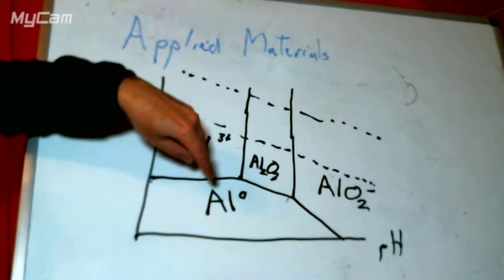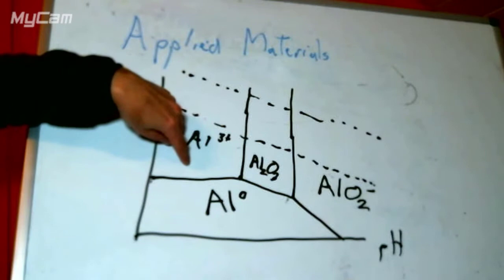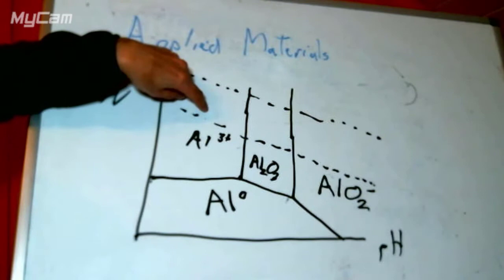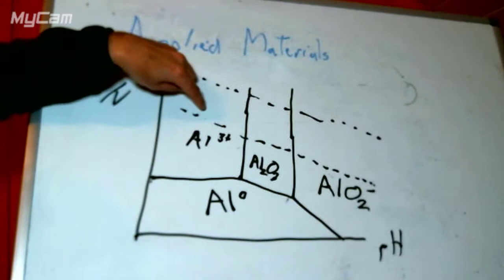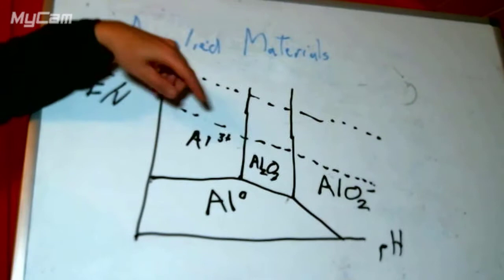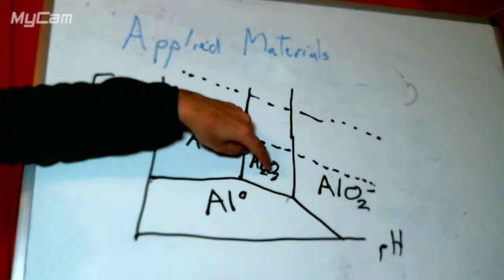If we're at low pH and allow it to get to a normal voltage, which is up here in water, then our thermodynamic endpoint would be aluminium³⁺ — that's where we would expect all of our aluminium to go eventually, and obviously we're going to corrode the aluminium away. If we're across here in a different situation, we are more likely to make aluminium oxide, Al₂O₃.